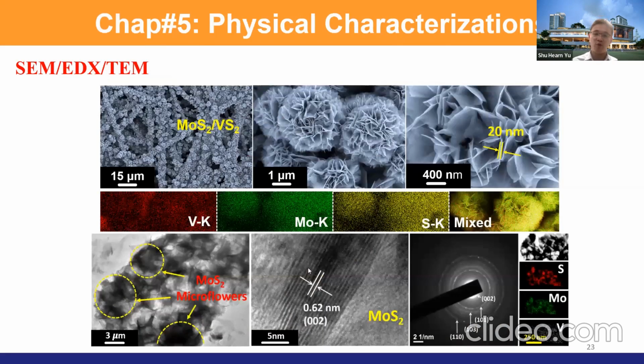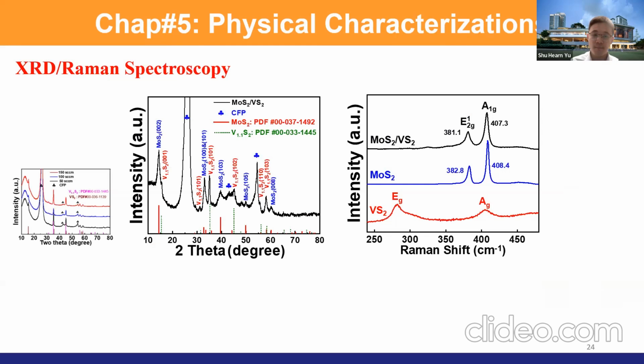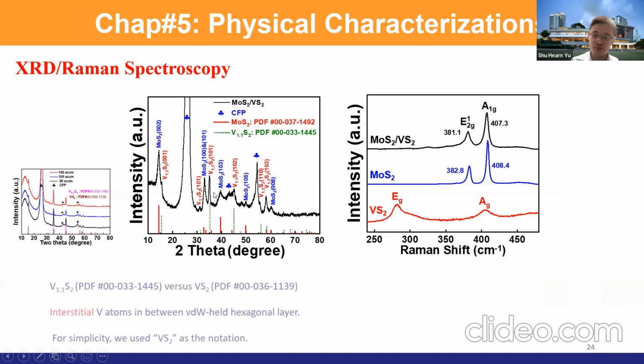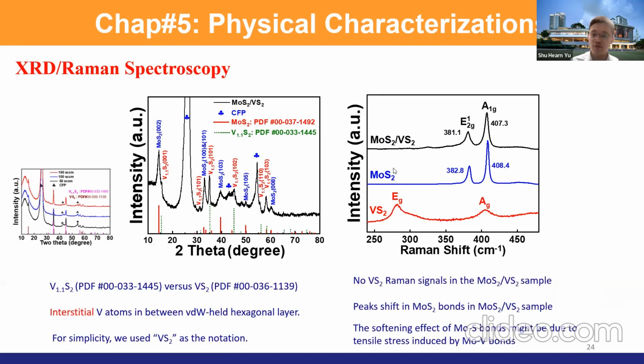So this is a very interesting doping process. It's a solid diffusion process. And then we perform the XRD and we find that there are MoS2 and VS2 structures. We also perform Raman, and there is no VS2 Raman signal from the sample because the VS2 is underneath, so it cannot be detected. And we find that there's a peak shift in our sample as compared to the pristine MoS2 grown on the carbon fiber paper. So this peak shift means that the doping effect is doing something behind, so we can change the chemistry of the electrodes of the MoS2.